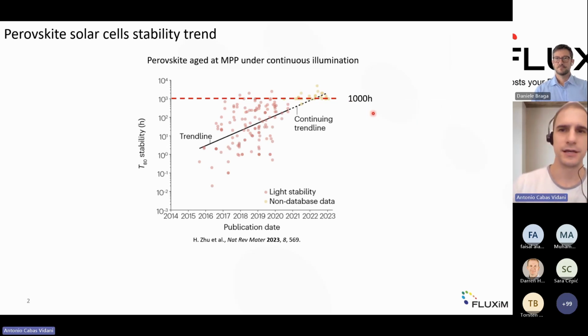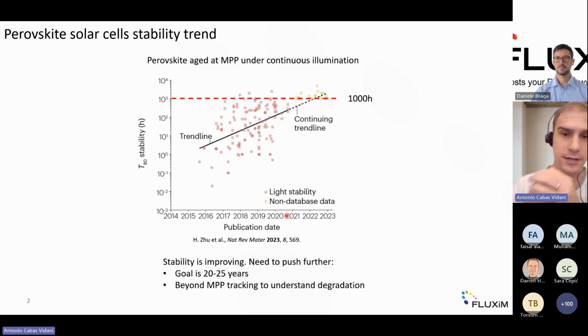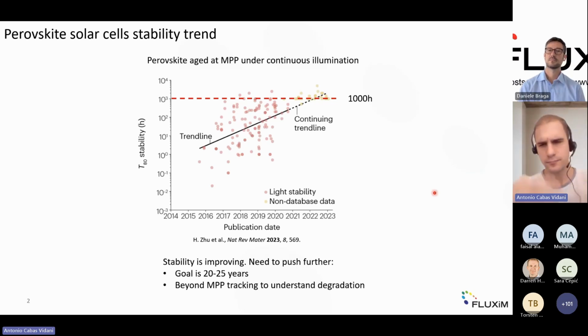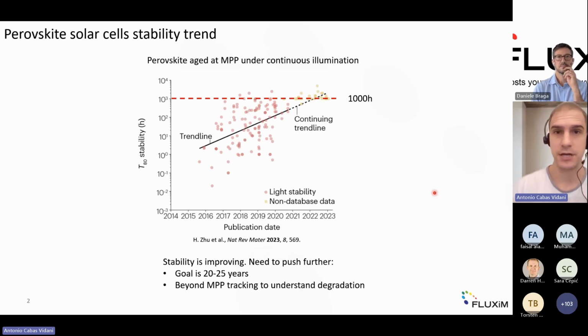The fact that perovskite lasts for 1,000 hours is intended as after 1,000 hours, it reaches 80% of the initial performance. This is T80 stability. Now we're on a good track. We clearly see the improvement, but we need to push further, because the goal is 20-25 years in order to be a good match for silicon solar cells, for instance. And overall stability is a rather complex topic, so we need to move beyond just MPP tracking under continuous illumination, right?